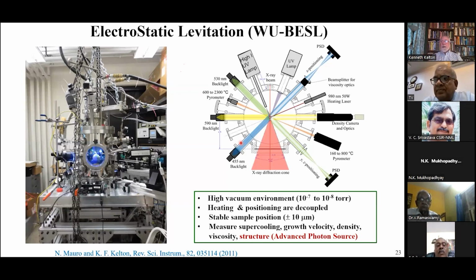We then use active feedback, computer active feedback, to control the voltages to keep it sitting there. We can keep the sample stable to about plus or minus 10 microns. And these are small samples, about 3 millimeters in diameter, but we can keep them very highly positioned. The chamber is under high vacuum. We use lasers to heat the sample once we have it levitated. Because we're heating the sample, we have to have high intensity UV lamps on the sample to restore charge, because when you heat the sample, you're going to have evaporation and that will carry off charge. So we have to replenish that charge. But we can do this, and we can do processing in a very stable way.